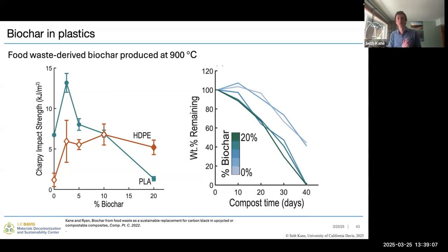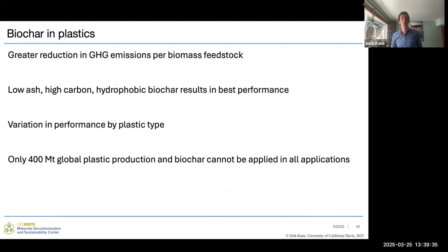However, there are then some interesting interactions. For example, if we wanted to have our PLA biodegrade at the end of life, the addition of that biochar does decrease the composting time of that PLA, which in some scenarios might be beneficial. And that's a result of it allowing more moisture to travel into the structure of the PLA and allow that hydrolytic degradation to occur a little bit quicker. So there's potential ways that we can integrate this into different plastics for different applications. Exactly how we do that will depend on the exact application of those plastics, which might be a little bit more varied than our application of our concrete, as well as the higher variation in properties between our different plastic types.